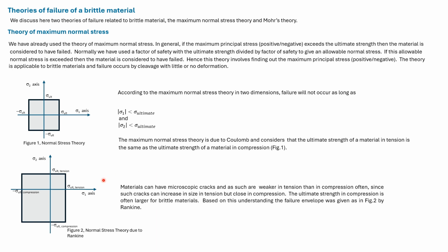Materials often have cracks, and under tension the cracks will increase in size, and under compression the cracks will close. So in brittle materials, the ultimate strength in compression can be larger than the ultimate strength in tension. This failure envelope was given by Rankine based on that understanding.